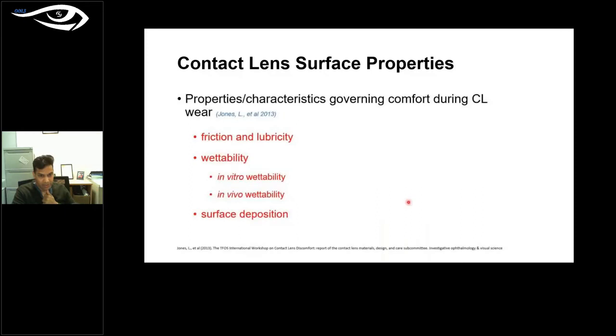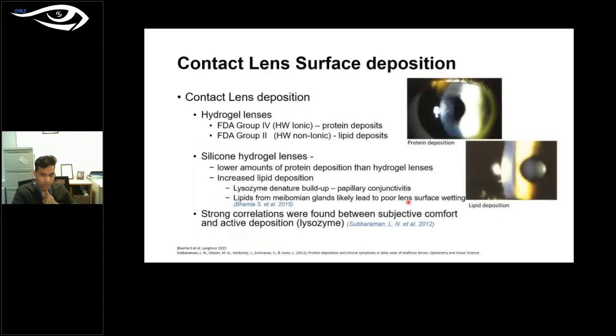Now, what this means is there are not sufficient tears, the lens is drying up, and this will attract deposition. So there is surface deposition. And what do we know in terms of surface deposition? Surface deposition depends on what kind of lenses we are dealing with, whether it is hydrogel lens or silicone hydrogel lens. Hydrogel lenses, as we all know, are classified according to FDA into 4 groups. So we have FDA group 4 and group 2, which are high water content contact lenses. Either ionic or non-ionic, both are prone to deposition. FDA group 4 is more prone to protein deposition, whereas FDA group 2 is more prone to lipid deposition.